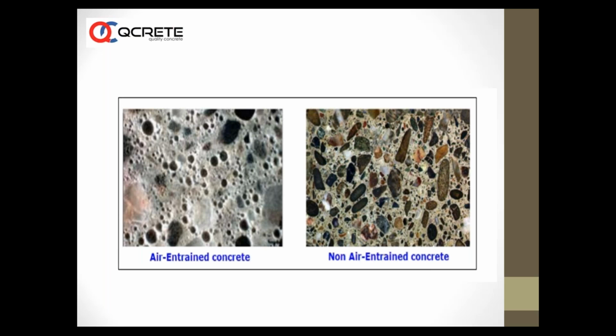When the temperature rises, the frozen water, the ice, becomes water again. It goes back to its natural position, and the air bubbles also come back to their natural position. This continuous freezing and thawing effect on normal concrete gives rise to stresses and cracks, and durability becomes questionable. In the presence of air bubbles, they accommodate the expanded volume of water and hence reduce the stresses and reduce the cracks.